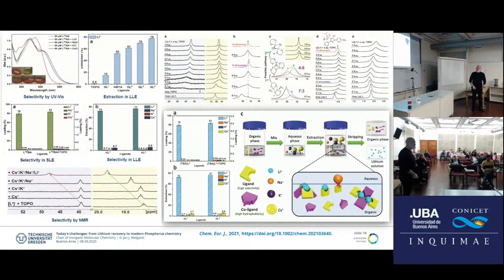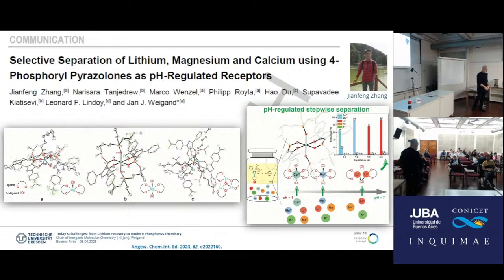Now that continued in one paper, also not going to go into detail, and when we realized this, we changed the position a little bit. We changed the NO2 group to a CF3 group. And what happened now is that it became selective by pH. So cutting a long story short, the one you've seen before, we can separate now from the alkali metals. But what is more important, if you look into brines, they typically are also associated with magnesium and calcium.